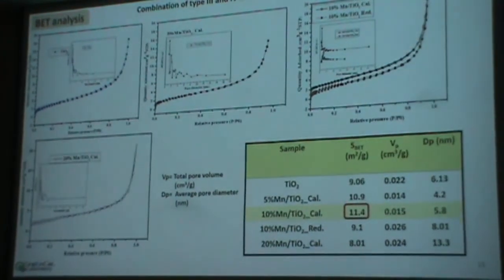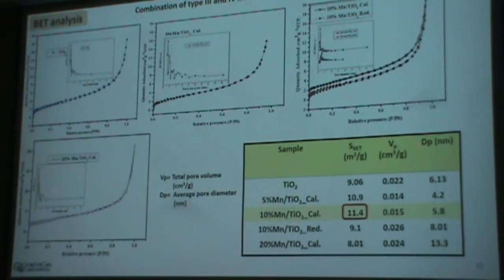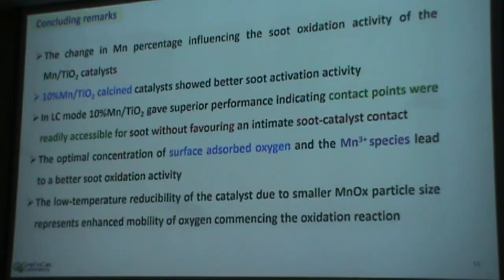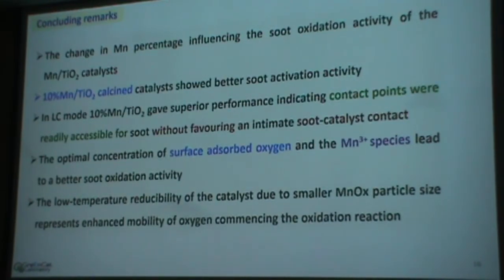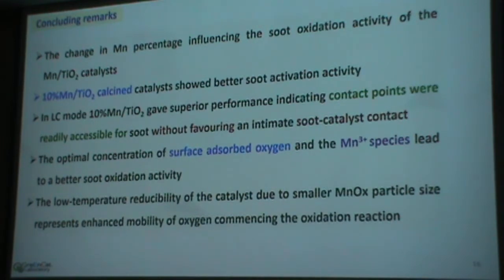Surface area is not too important in the oxidation reaction, but for the dispersion of metal it plays some role. You can see that although the surface area is less, in 10% Mn there is a slight increase in the surface area. This may be because of changing morphology, which may provide some dispersion of Mn species on the surface, and because of that it shows activity at low contact mode also. That means we have concluded that loading of Mn is important for the soot oxidation reaction, and 10% loading was found to be optimal due to the optimal combination of lattice oxygen species and Mn3+ species, and the morphology of the catalyst also plays an important role.